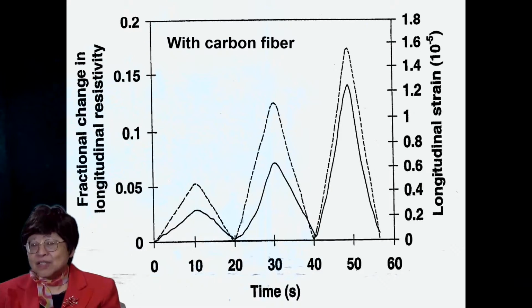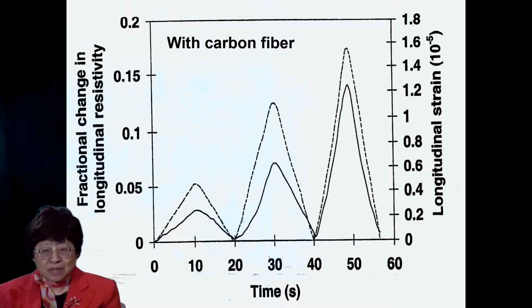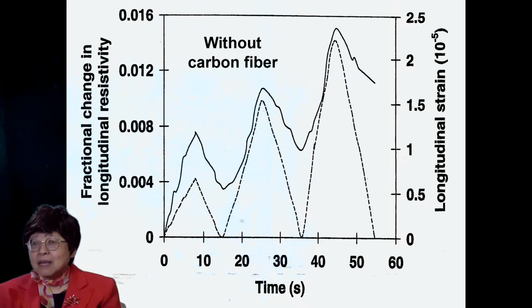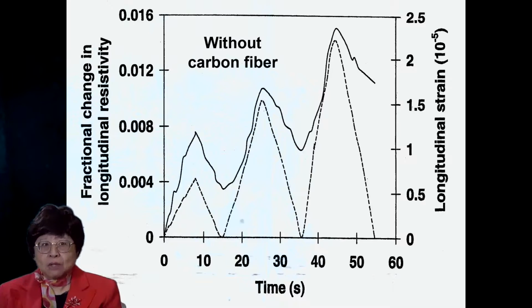This is the same thing, but under tension, a 4-probe method again. And under tension, the resistance increases, just the opposite of compression. And note that is very nicely reversible. However, if one takes away the carbon fiber, there's still an effect, but it's not totally reversible. Also, the magnitude of the effect is much less than the case with carbon fiber.